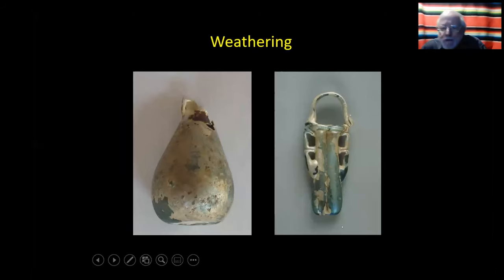Glass does have one major enemy, and that is water. The alkali in the glass is soluble to start with and remains soluble. And it's easily leached out during archaeological burial if the burial environment gets wet. And so most of the glass in the Mediterranean region gets wet every winter and then dries out. The bangles you saw in the previous slide were found in a dry tomb, and so they never got wet. And so they never suffered any of this leaching of the alkali.